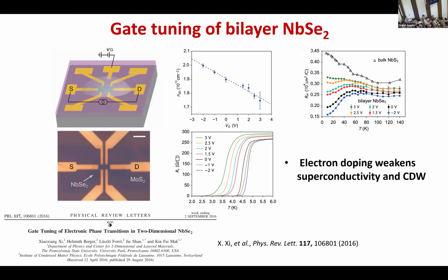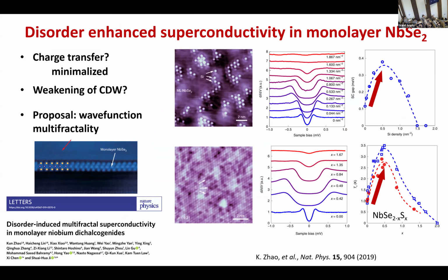So let me just move on. Let me end this part by showing you another interesting thing about the MBE grown samples. At that time, also at Tsinghua University, my colleagues grew this niobium diselenide also on bilayer graphene. What they actually did is keep the same system, because they know that the monolayer is very easy to degrade, so they capped it with amorphous silicon. And when they took out the sample and measured, they saw that the TC is pretty high, like 3K or 4K, much higher than what the Stanford group reported.